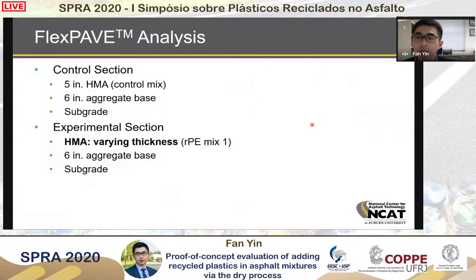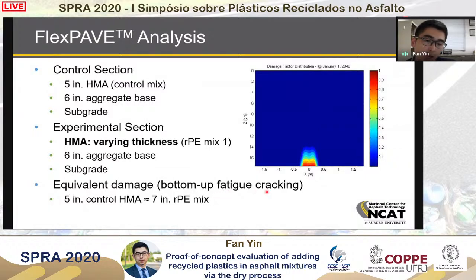And finally, we use all these results to do the FlexPAVE analysis to predict the fatigue performance in the pavement structure. In this case, we were looking at bottom-up fatigue cracking as the main mode of distress in the evaluation. When we do the prediction, we fix the pavement structure for the control section. We adjust the thickness of the plastic-modified mix section, trying to match the equivalent damage due to bottom-up fatigue cracking. Based on our simulation results, we found that we need a 7-inch layer of the plastic-modified mix to provide the same damage resistance as the control mix using only 5 inches of hot mix asphalt. This is related to the reduced fatigue resistance of the plastic-modified mix, so we need to increase the thickness so that we can reduce the strain at the bottom of the asphalt layer so that it can improve the fatigue resistance.